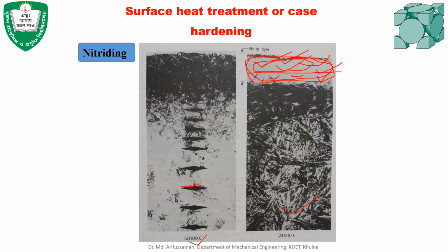So the Vickers hardness will be less. The longer the diagonal, the less the hardness, so these are almost similar length diagonals. But as you move to the surface, the diagonal starts to reduce. That means the hardness is higher at the surface. Okay, that's how nitriding works.